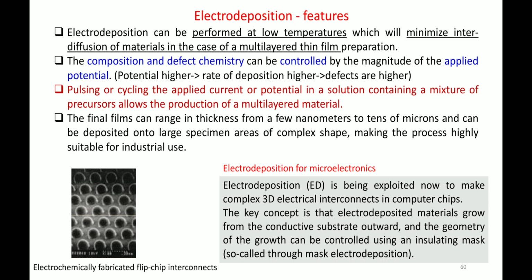So you can also use a mask which is non-conducting. Anything which is non-conducting can act as a mask, and the remaining area of the conducting material will be kept open, so that you are able to deposit that material only in that region. So that is the advantage of this electrodeposition technique. You can see there are electrochemically fabricated flip chip interconnects, and the SEM image of those interconnects is shown in the image, where you can see that the shape is complex, but still on that type of complex shape we are able to deposit a uniform deposition of metal.